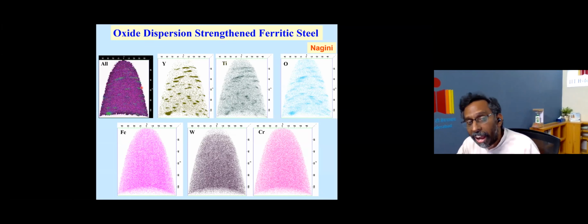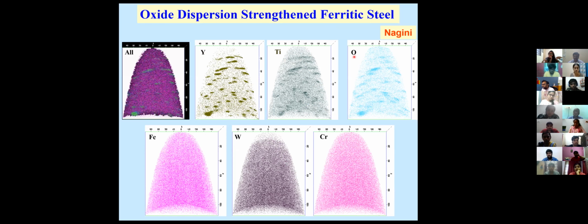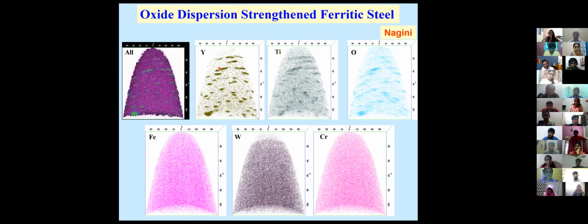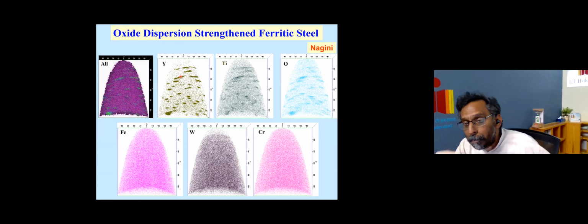It is very fascinating. And just to tell you, how does it show? For example, this is a steel, the same steel I was showing you. If I look at how iron is distributed, this is called elemental mapping of iron, elemental mapping of tungsten and chromium. You see all of them are uniformly distributed. But if I look at the mapping of yttrium, titanium and oxygen, you see that yttrium, titanium and oxygen are inside these particles. And that's why we say this is a particle made up of what we call Y2Ti2O7. We have been able to establish the composition of this particle by analyzing this data. All this is possible.